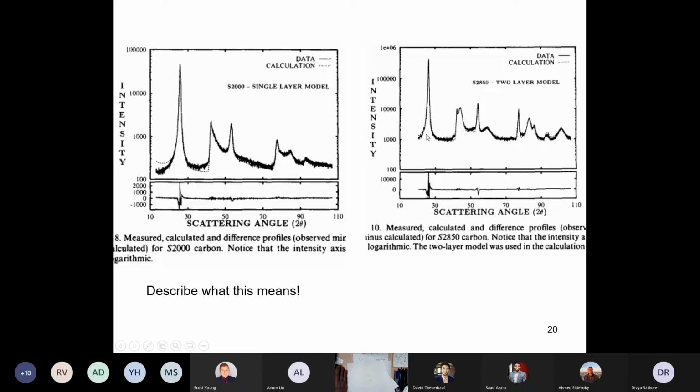And what do we have? We have a very sharp first peak. This is telling us about the fact that many layers are stacked in a parallel direction. Several hundred are perfectly parallel. And then, if you look carefully, you'll see a very sharp peak and then a little bump next to it. So what's happening now is you're starting to get the AB stacking of 2H graphite.